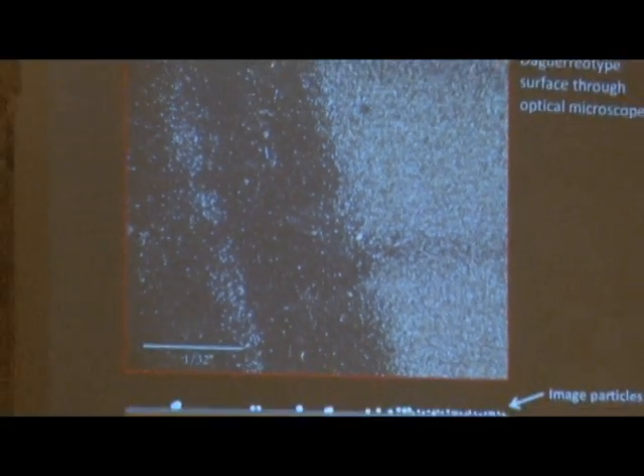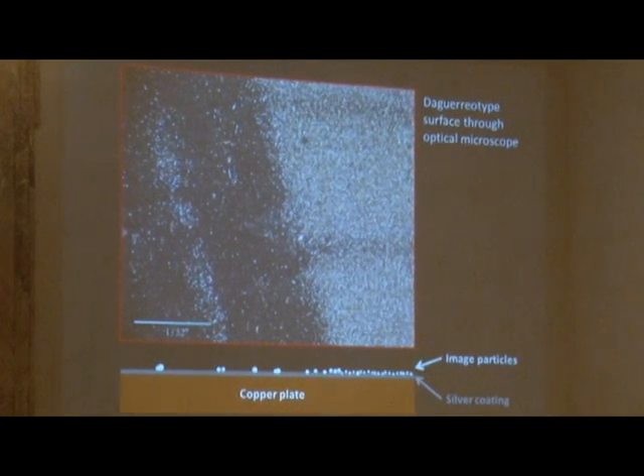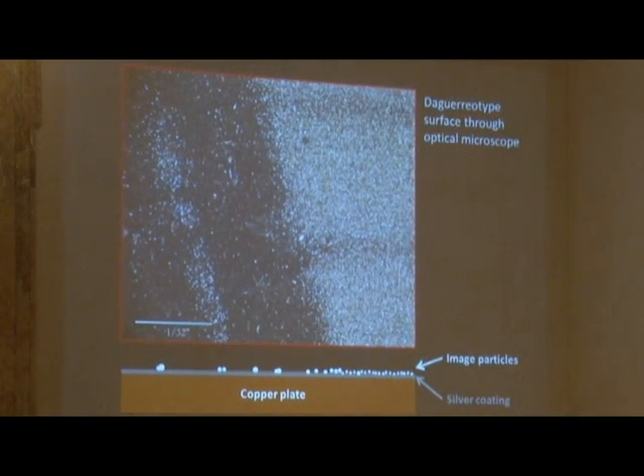At this magnification, you can see the granular nature of the surface. To the right is a higher area where there are small image particles snuggled up to one another and scattering light and looking white. And on the left, there are much fewer image particles. You still see the white dots, but it's reflecting the black lens of the microscope I took this image through.